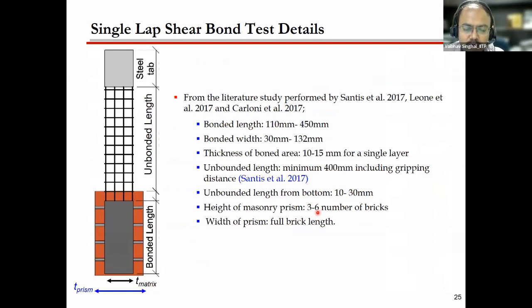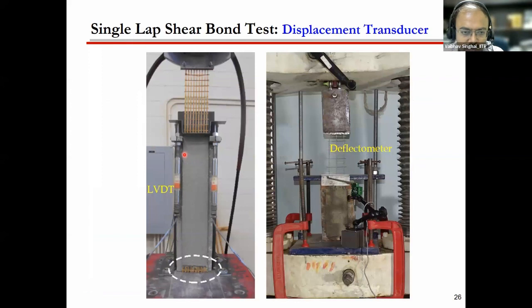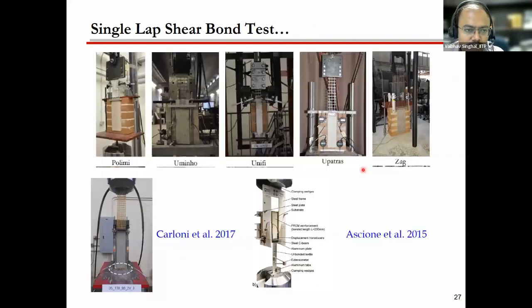From the literature, we find quite a wide range of specifications and specimens which they have used. This is how a typical single lap shear bond test specimen looks. You will have some bond length and some unbonded length, and then some gripping length which is used for pulling it in the upward direction. These are some pictures of test setups. This one is from another lab and this is from the IIT Patna lab. And these are from all over the world, what they have adopted for this single lap shear bond test. In one of the labs, they have also done the double lap, where the fabric is going in the forward direction and also in the backward direction.